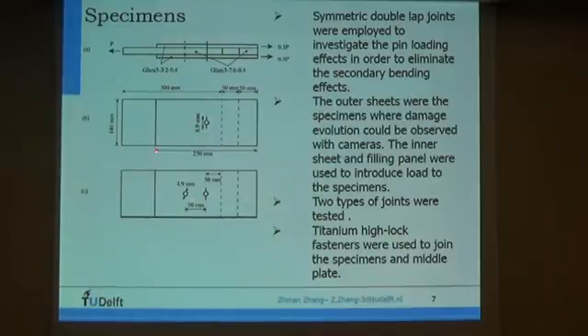From these 2 pictures, we can see there are 2 kinds of tests we designed for this investigation. The only difference between these 2 tests is that for this test there is only 1 pin pair, and for this type of test there are 2 pins for this specimen. And the pin is a titanium Hi-Lok fastener used to join the specimens and the middle plate.